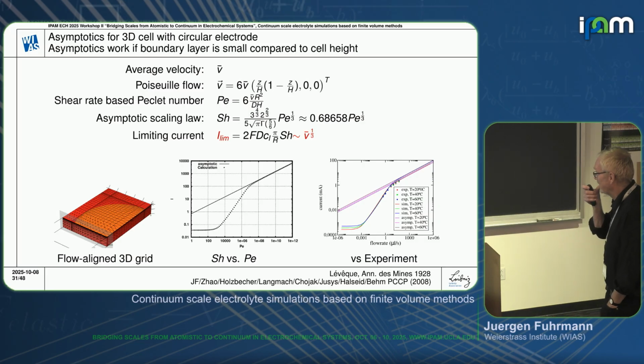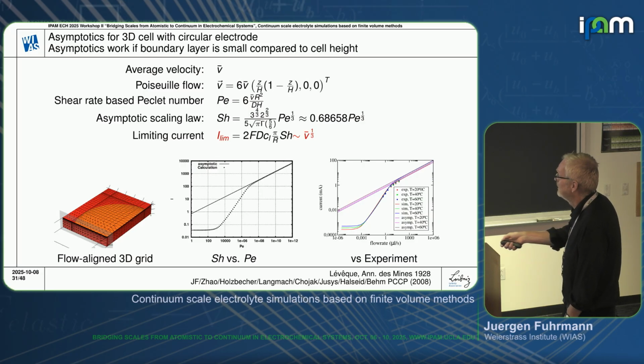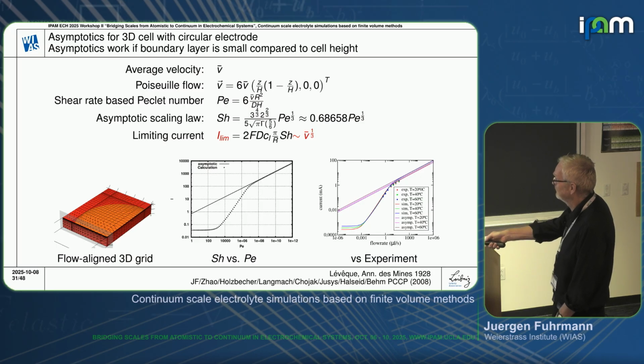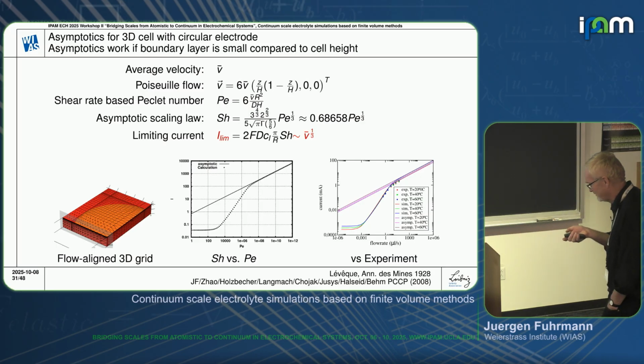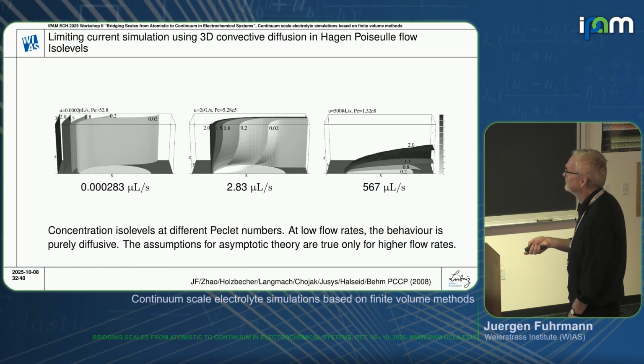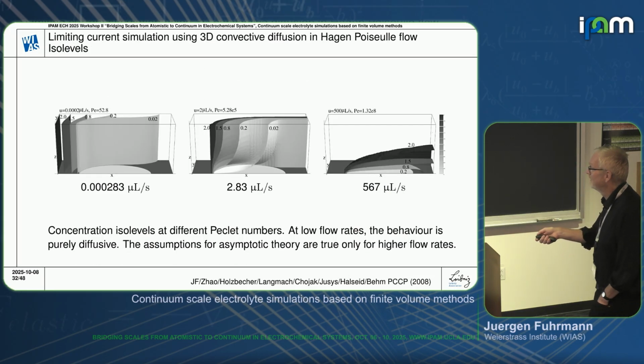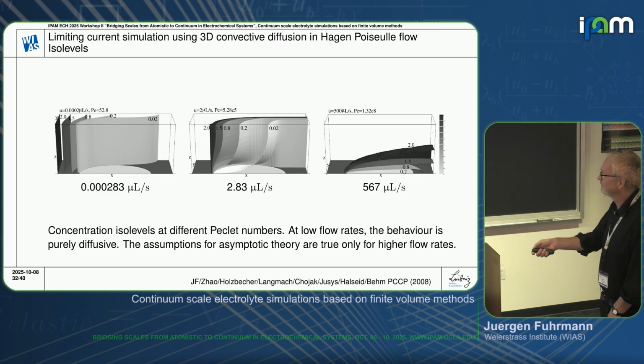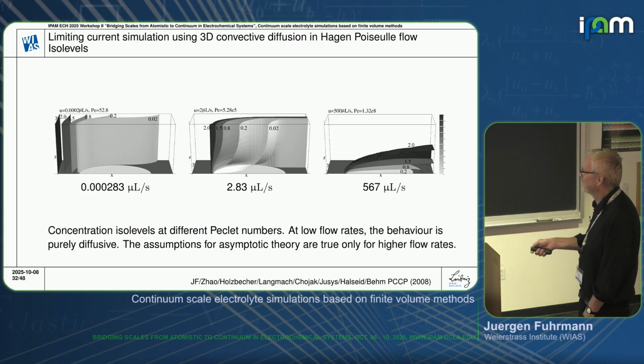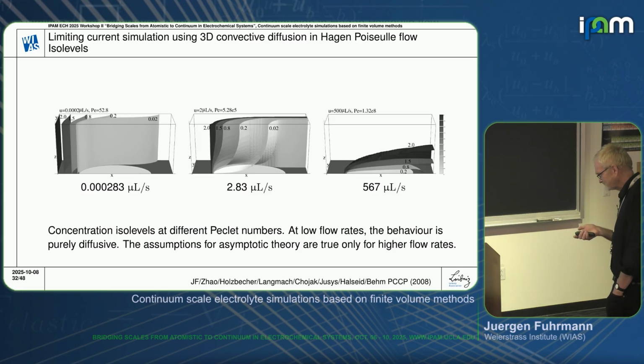So that means that in order to understand this, for instance, we have the dependency of the limiting current on the diffusion coefficient. You can use this experiment, for instance, to measure diffusion coefficients. It's important when you interpret it in this way. And the fact is that, depending on the flow rate, for small flow rates which have been used in the experiment, we cannot use the asymptotic theory because the hydrodynamic boundary layer is too large and it just correlates with the domain size. But for larger velocities, we see that this boundary layer is smaller.